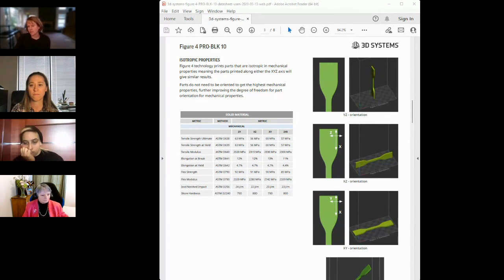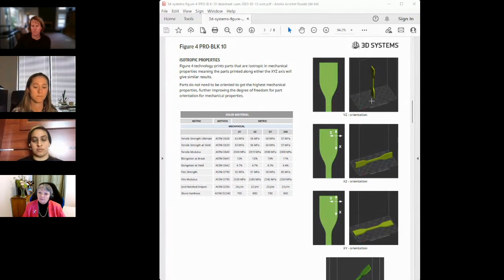So in the case of figure 4, we just do 4 different orientations, which are shown in these pictures. And this is a case where we do have to do extra finishing. Our default orientation for printing is in the Z-axis, and that puts the supports on the end of the sample, which means we don't have to do anything special in order to test those. But when you have samples on their side or at an angle, you're going to have supports in this area, and we do finish those areas so that there's no witness marks for the testing.